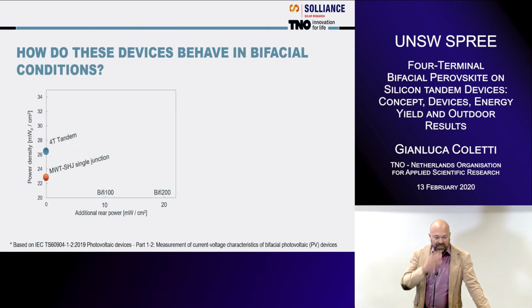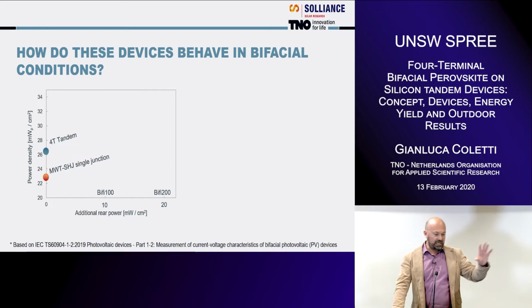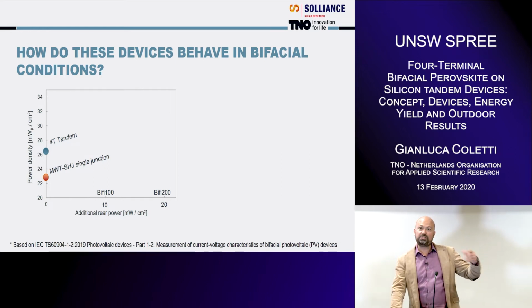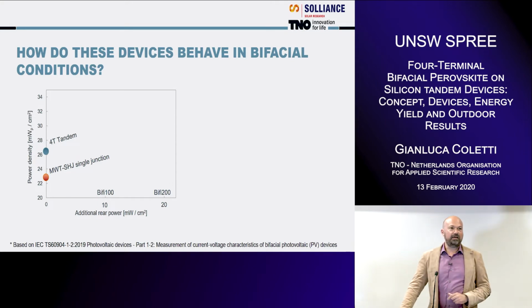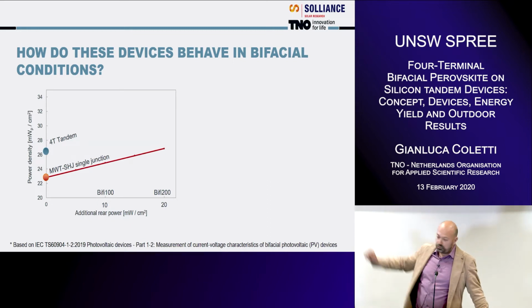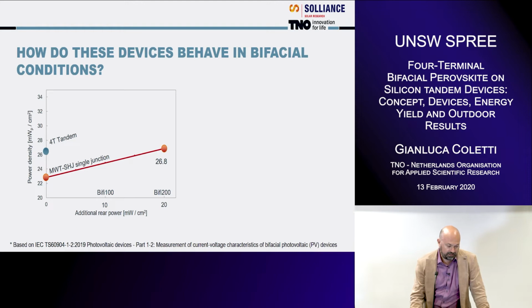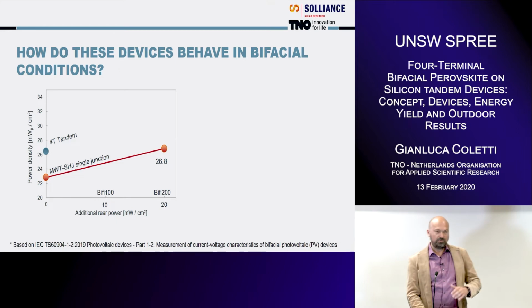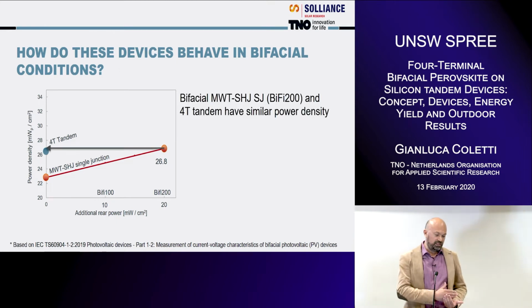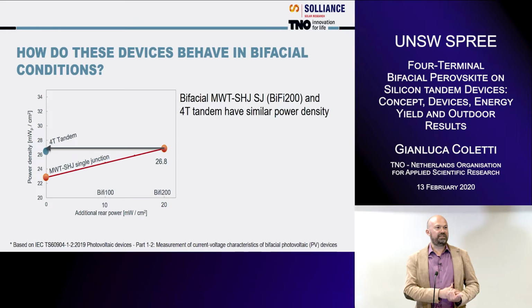So how does this device behave in the bifacial condition? We start, you remember before, there was 23% for the MWT-SHJ single junction device, and 26.5% for the tandem. These were with zero irradiance from the rear side. If you add the so-called BiFi100 or 200, you end up with a power density of 26.8. Now this is important because 26.8 is very close to the 26.5 power density of the monofacial tandem device.